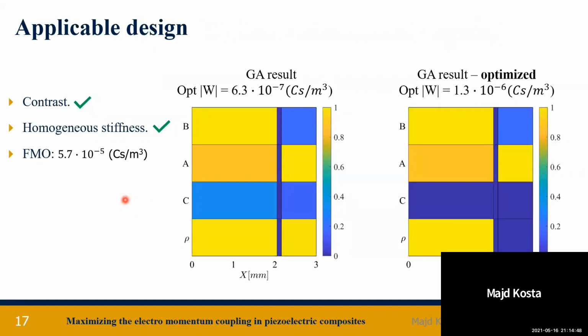So with that being said, we still want to search for the best optimal applicable design. And to do that, we take the result that has been obtained before from the discrete material choice and optimize it over the 2 properties that can be synthesized, which is the material stiffness and mass density. And from that point, we can go anywhere because the structure already has a contrast within it, and it already has a value of W. And in here, you can see the optimal design where once again, the stiffness is homogeneous and the mass density exhibits contrast.